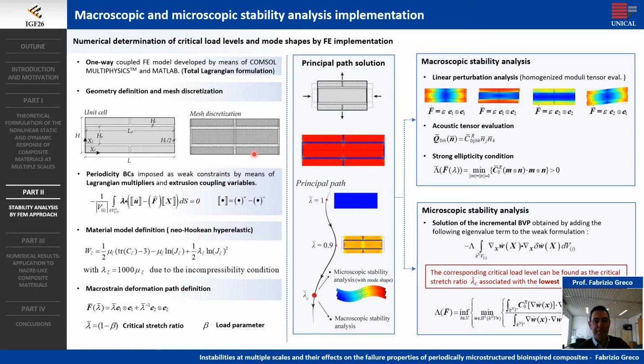To solve the problem, a specific script code has been developed by using the commercial code COMSOL Multiphysics for the computation, and the microstructure constituents are supposed to obey a quasi-incompressible neo-Hookean constitutive law. The composite microstructure has been subjected to macroscopic biaxial loading radial paths in the principal macrostrain space, governed by the macroscopic principal stretch ratio in the x1 direction.